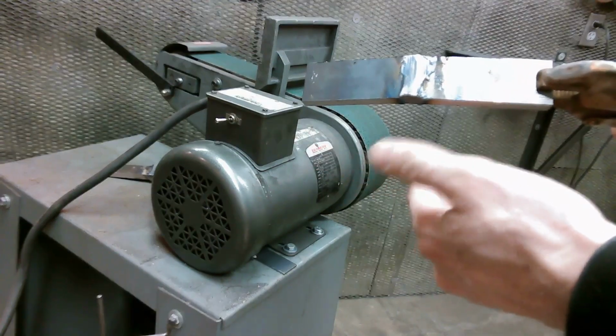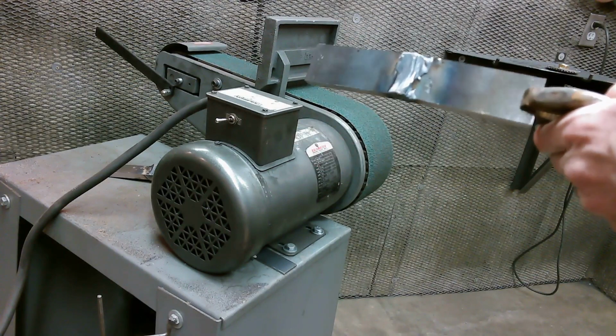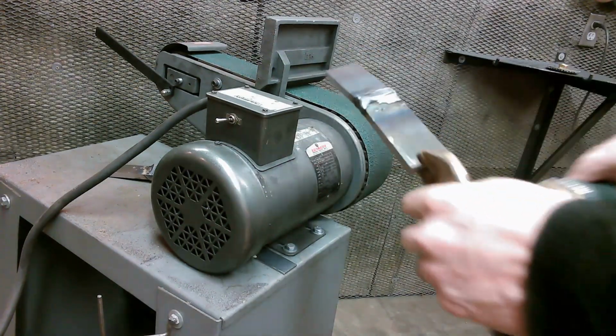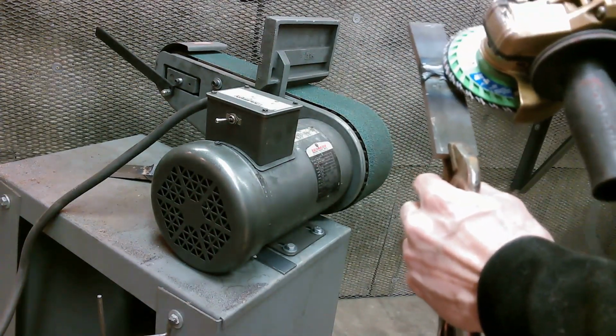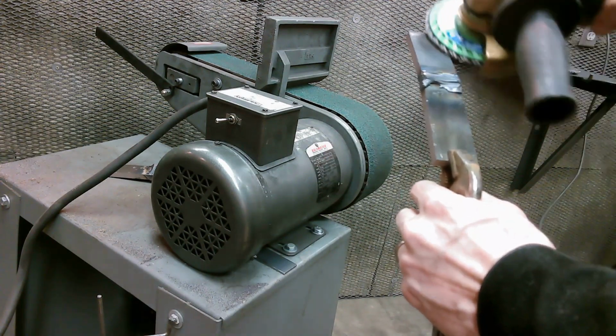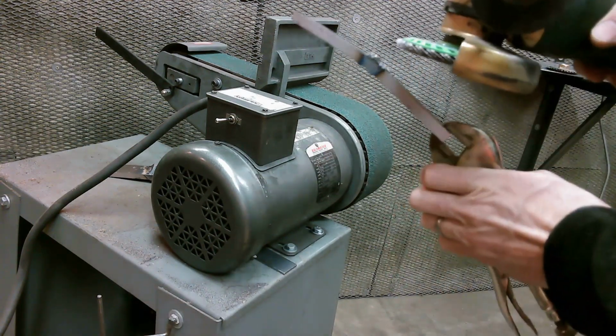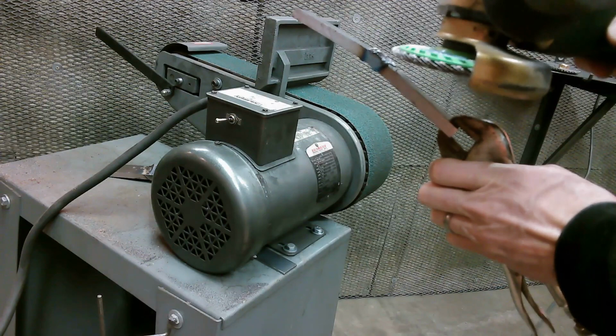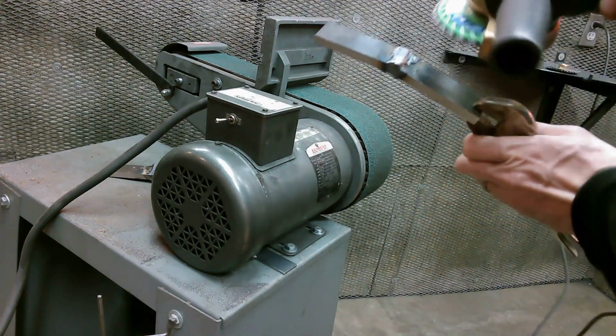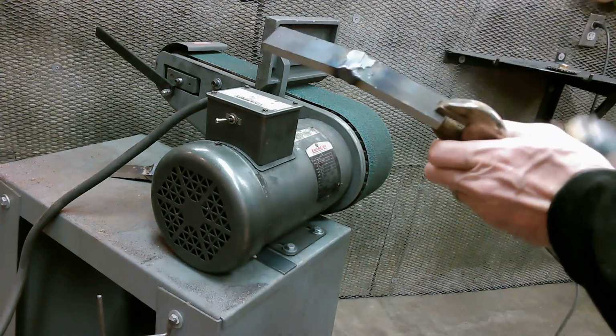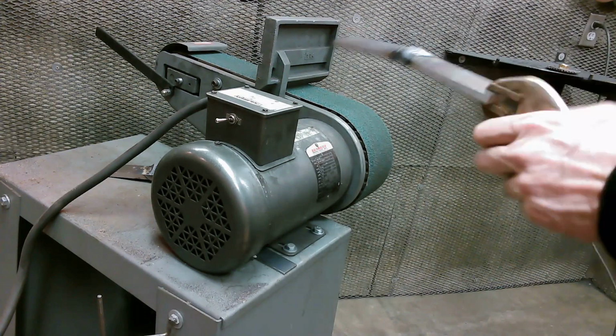And so if you are going to use, say, a handheld angle grinder, you want to make sure that you're taking the disc across this direction so that the scratches go lengthwise and not this direction. Otherwise the scratches are going to go perpendicular to the workpiece, and that's bad for bending them.